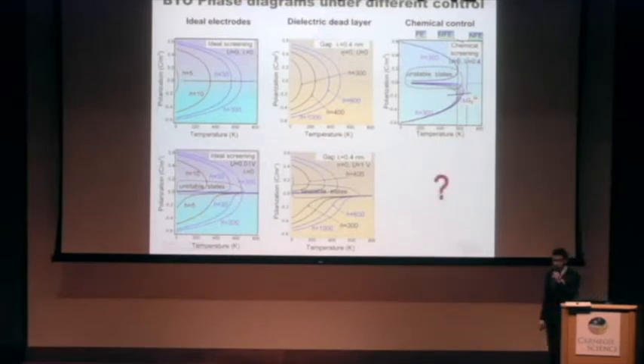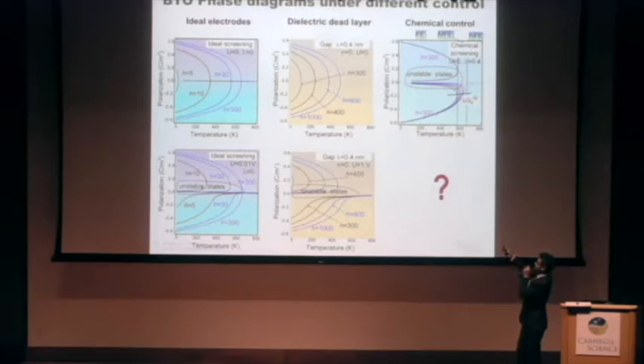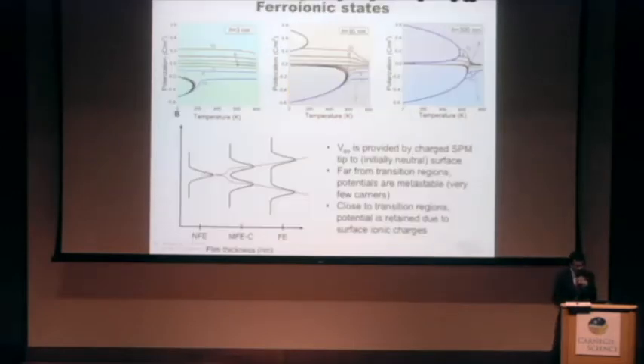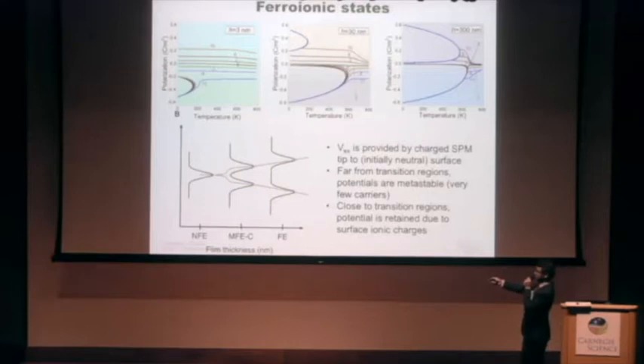when we want to try to apply a potential for this particular state here? That's the more interesting case, and so I'm going to explain to you what happens here, and it's quite interesting. If we start with a 3-nanometer film, you will see that at 3 nanometers, there's only one polarization state that's stable, and it's only at very low temperatures. But by applying potentials, you're able to stabilize all different types of polarization states here.